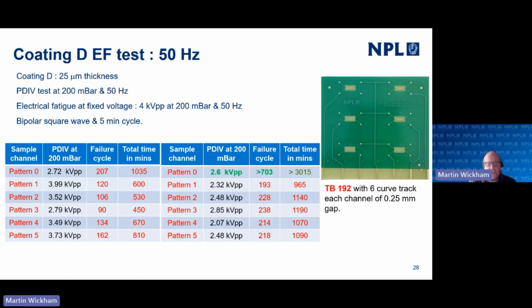Now, this is another coating. It's a 25 micron coating, different chemistry again. Again, testing by the same parameters, 4 kV at 200 millibar, 50 hertz, 5-minute cycle time. One of these hasn't failed. We ran it to 700 plus cycles before we stopped, but we have got sort of 11 out of 12 failures here.